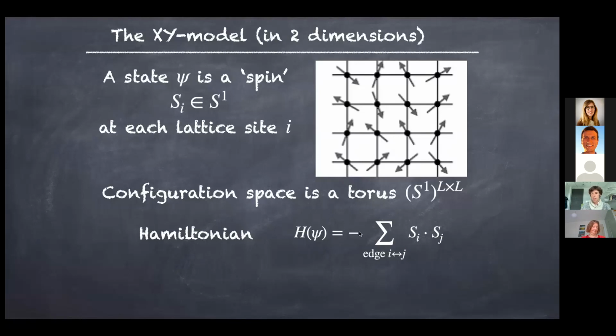And what you do is you put a minus sign in front, and sum over the dot product of these 2 spins for every adjacent pair of spins. So for each edge, I'm going to take the dot product of these 2 vectors, and I get a contribution, and I sum those all up with a negative sign. That gives me the Hamiltonian for this system.